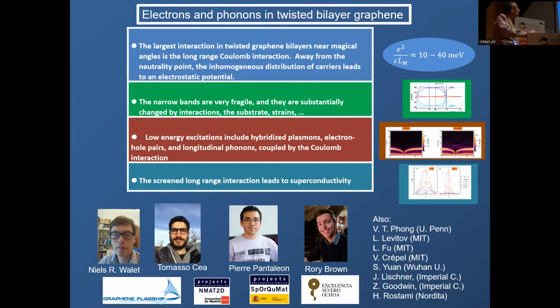Third, if you study superconducting pairing through electron-electron interactions, you have to worry because there is a complex situation where the electron-hole pairs, plasmons, and phonons overlap in the same region of parameter space. And finally, at the end of the day, this screened long-range interaction can lead to superconductivity. Thank you very much.